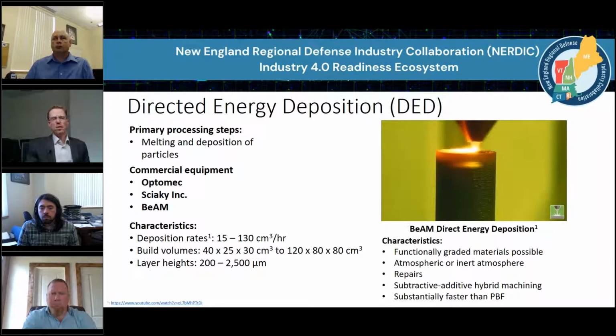Players in this space include Optomec, Sciaky, and Beam. You generally get some fairly large deposition rates, about 15 to 130 cubic centimeters per hour. Build volumes can be quite large. Some of these can actually be outside of machines where you don't have a controlled environment, thus allowing you to do repair type of activities, which is quite exciting.